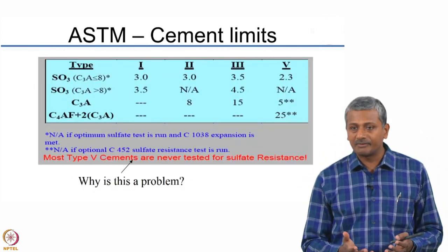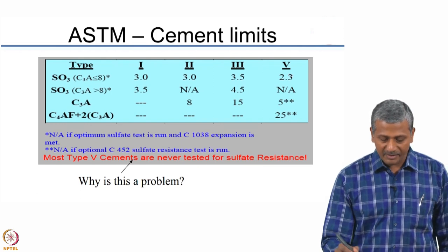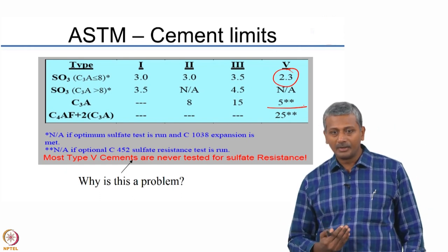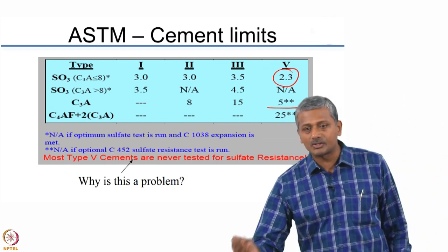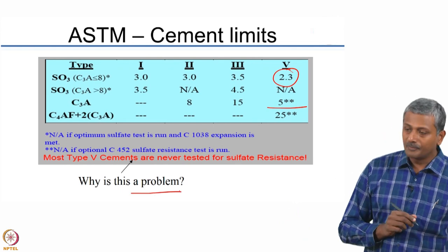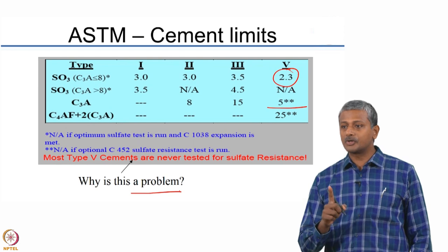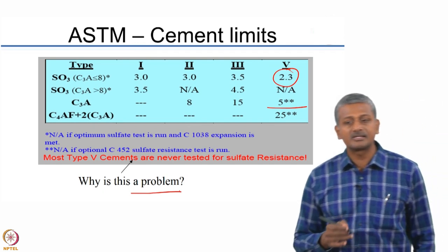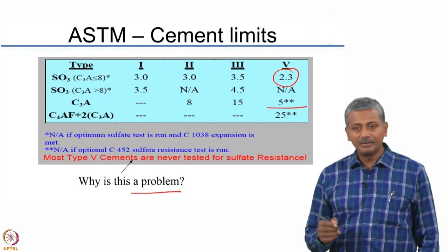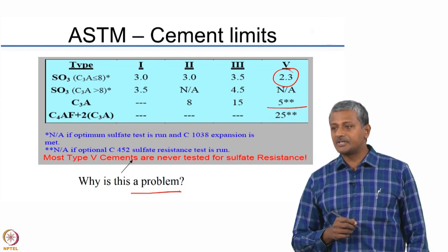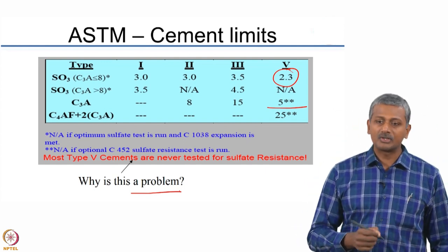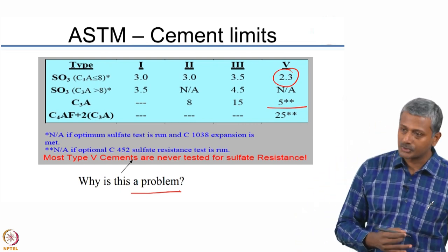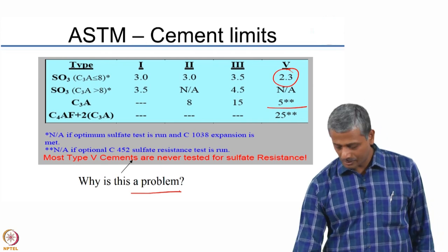Various standards give cement limits — for example, ASTM limits C3A to 5% for sulphate resistant cement, while IS codes limit C3A to 4%. However, often we say to use sulphate resistant cement and forget about it — a problem is that we do not test the sulphate resistant cement against the specific type of sulphate that is actually present. For example, in the case of magnesium sulphate, where the dominant mechanism is not ettringite formation but CSH attack in the long run, sulphate resistant cements are known to perform poorly. We need to understand the kind of sulphate present and test the combination of cement being used to ensure the best solution for the particular scenario.